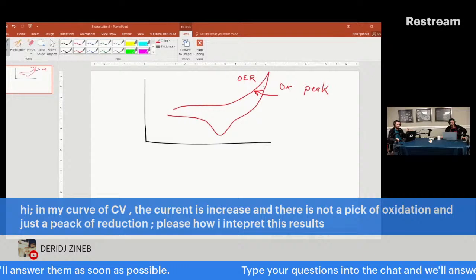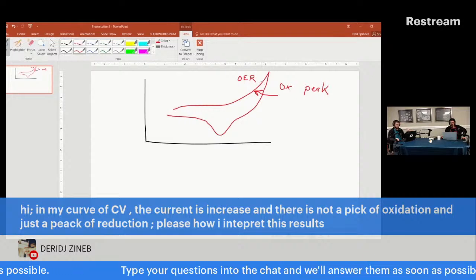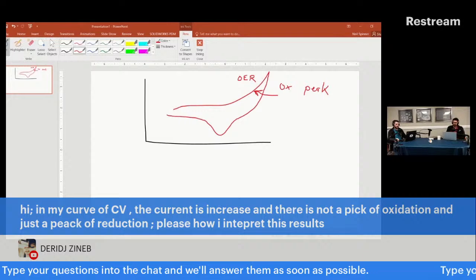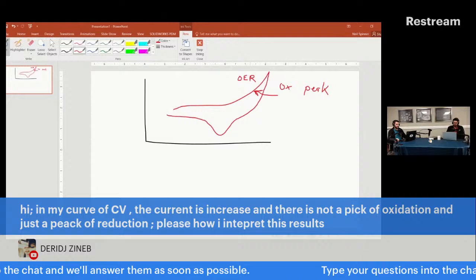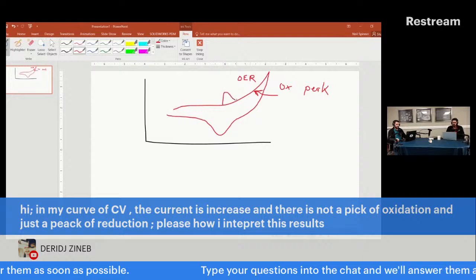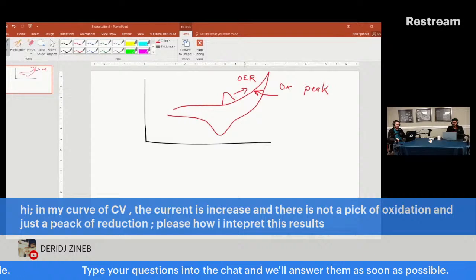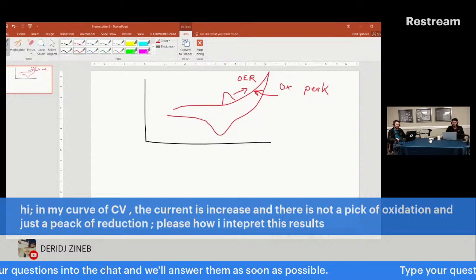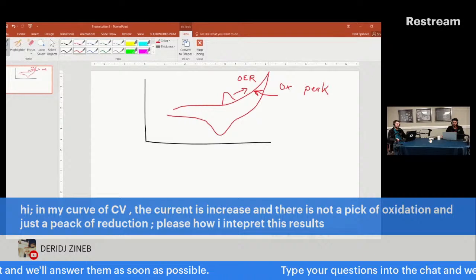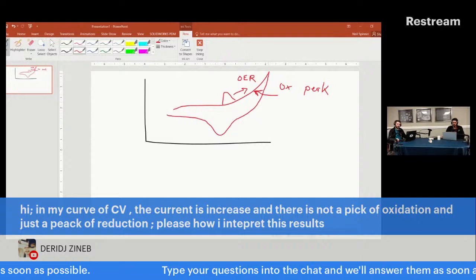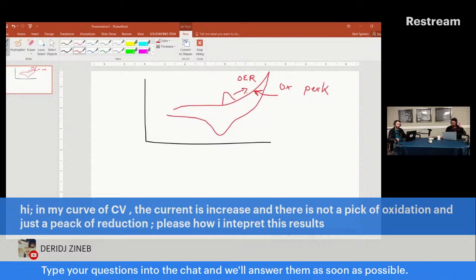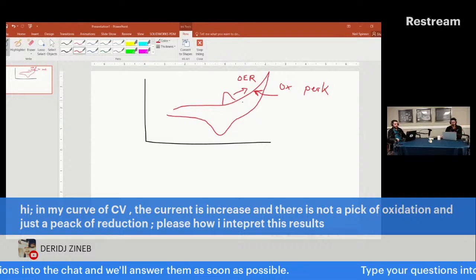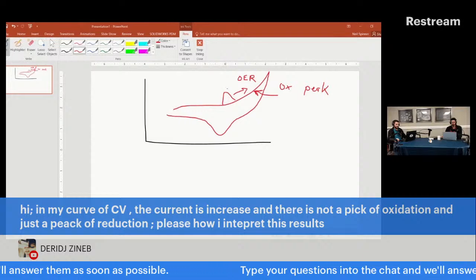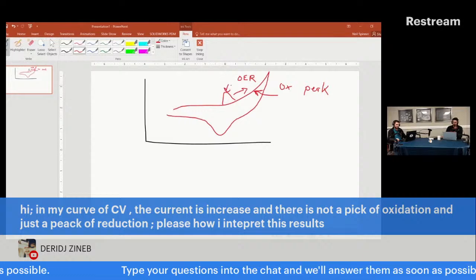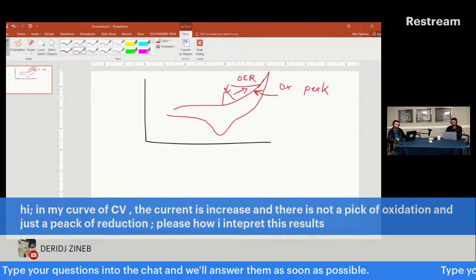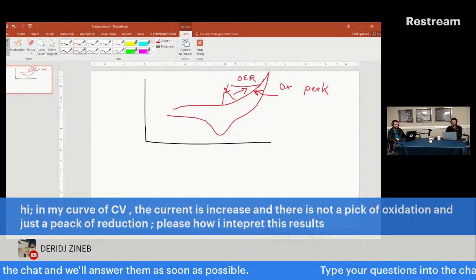So let's say whatever I have for a system, my electrode, my redox species, you might expect to see a peak here or something, but you don't. And so you don't get that oxidation current until you start scanning more positively. That's an indication potentially of a poor electrocatalyst because it has a very high overpotential required to oxidize something. And so the ideal situation is I would have a peak right here, but instead I end up oxidizing whatever the thing is that I'm trying to oxidize.